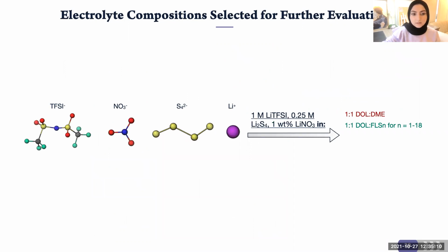So in order to understand the critical role of these fluorinated solvents in the electrolyte, we explored electrolytes containing 1 molar lithium TFSI, 0.25 molar Li2S4, along with an additive in each of the binary mixtures of the standard electrolyte that is usually used in lithium-sulfur batteries, and another electrolyte where the main solvent is DOL, and a co-solvent is a fluorinated solvent from the 10 selected candidates. And we included all of these electrolyte components in our study in order to have a realistic representation of the mixture, rather than just mixing the salt with the solvent.